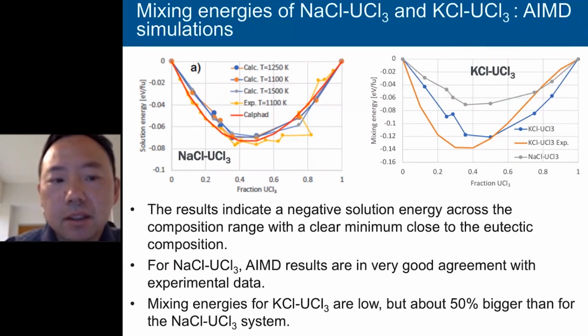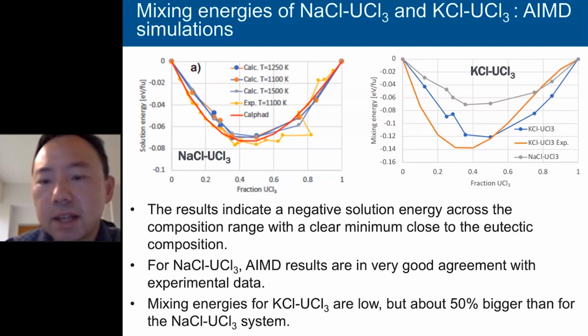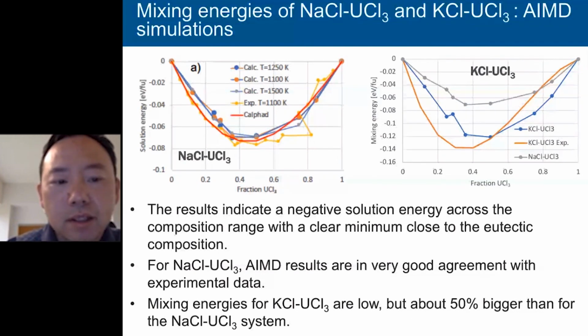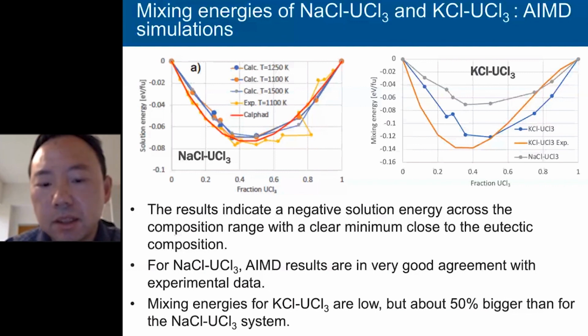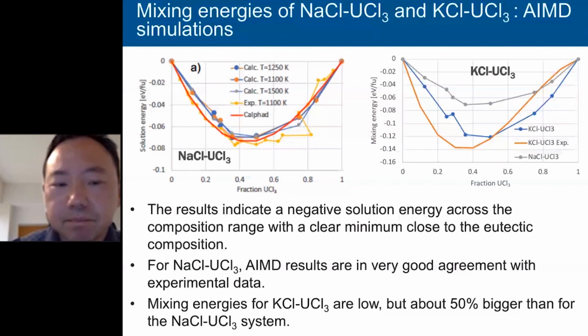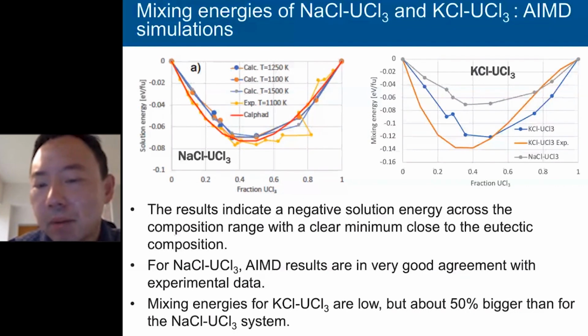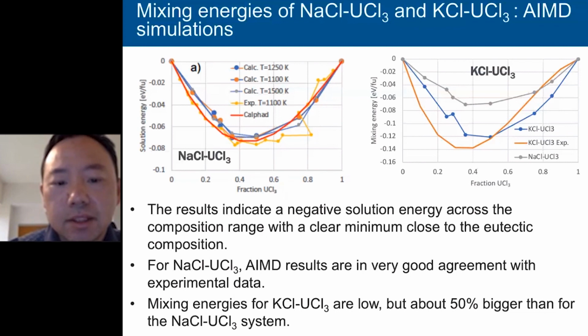And if you compare the sodium chloride and the potassium chloride systems, you can see that the mixing energies for the potassium chloride and uranium chloride are actually more negative than for the sodium chloride and uranium chloride systems. And also, one interesting point raised by David is that the minimum of this curve actually corresponds to the eutectic composition. So there's some connection between the thermodynamic properties and the phase diagram, which is a very cool correlation.